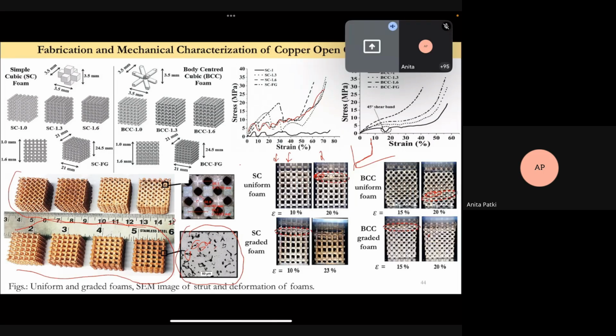So your strut is like this, and you're putting a load at 90 degrees. But when the struts are sharing the load at a 45-degree angle, then you get smooth curves, which gives you a ductile behavior. Okay. So now the art of this process is that you get designed pores and you also get some micro pores. So it can be really useful in certain applications where you need this type of pores.